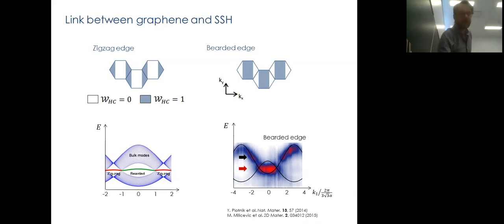We can do the same thing if we define our unit cell with a bearded edge, which is just shifting the unit cell by half a unit cell. And we have the complementary here. We just change the definition of J prime and J. All right. And so these edge states have been observed experimentally in photonic systems. Depending on where we are in the Brillouin zone, which is what I'm showing at the bottom right here, we can see that we have an energy state that appears and completely disappears at other positions in the Brillouin zone. It will be the complementary if we had the zigzag edge.